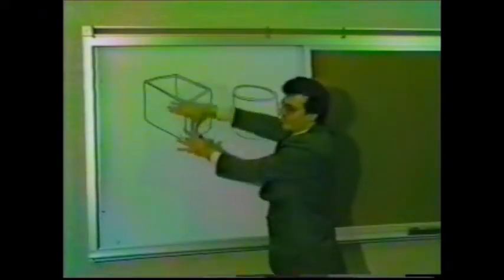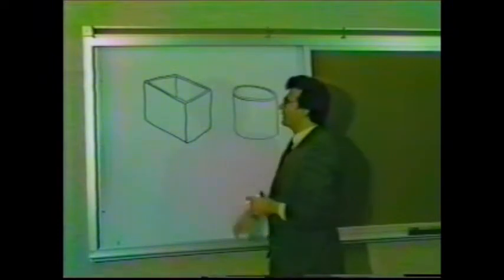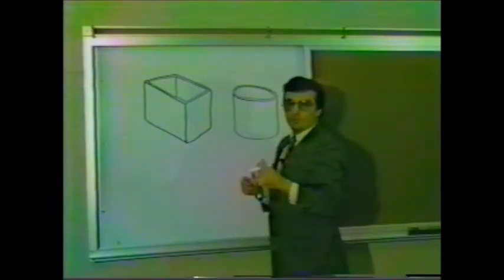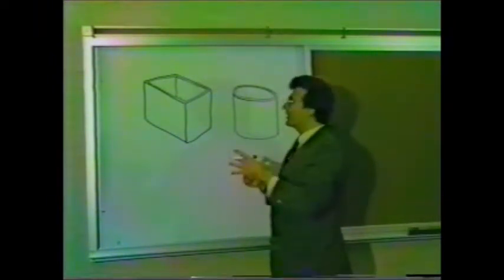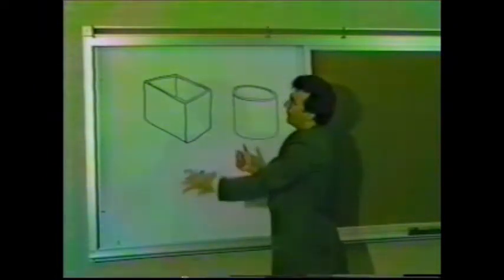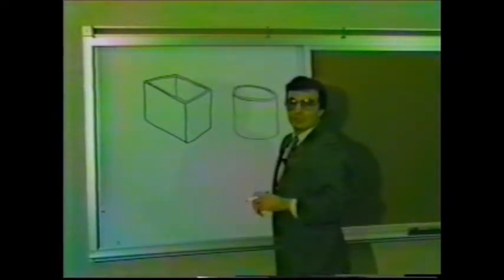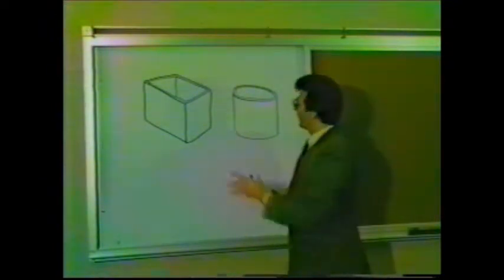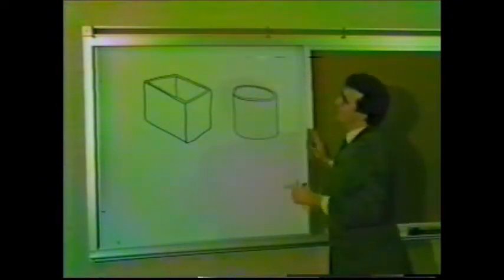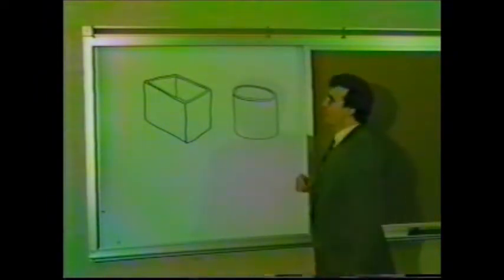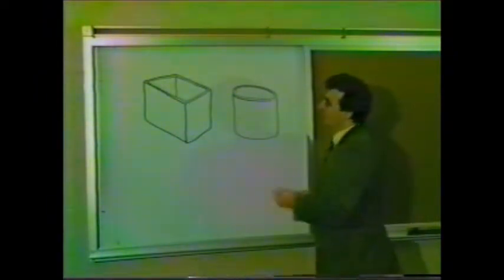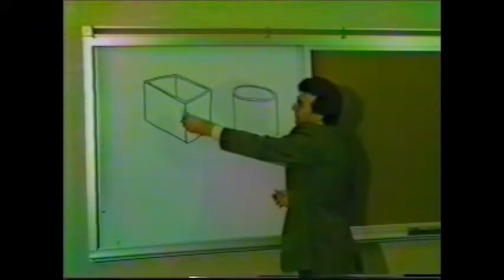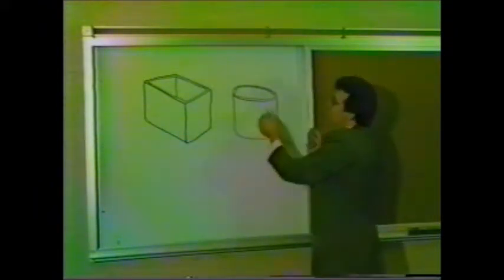The advantage of continuous casting is that you can have one essentially long strand of steel that comes out, and the product yield of the steel coming out is very uniform, and you don't have to discard nearly as much steel as you would if you were doing ingot casting. Now, I've drawn two shapes here, and there are two basic shapes to casting in continuous casting. You can have either a square or a rectangular mold, or you can have a circular mold.